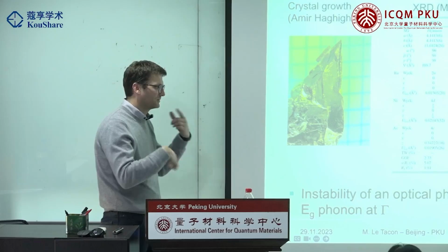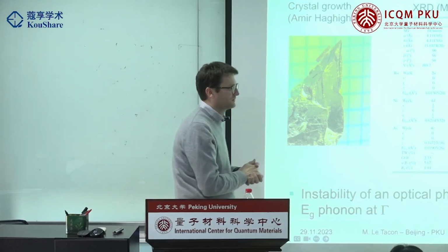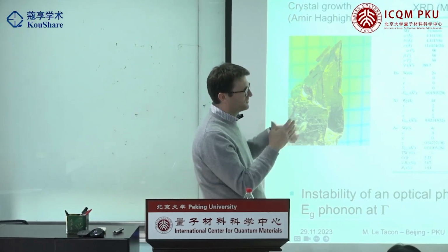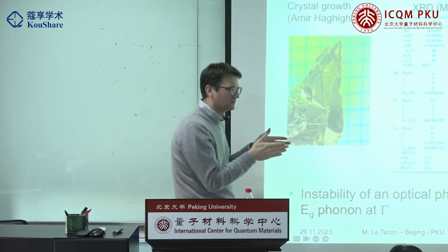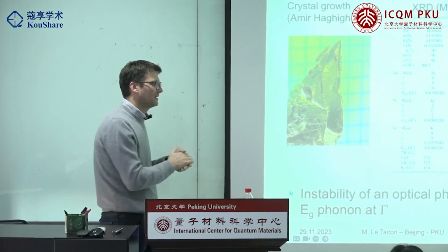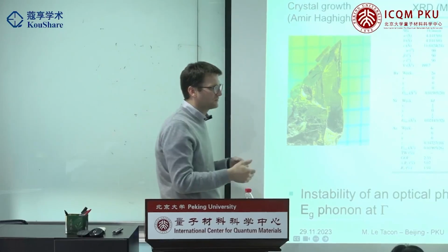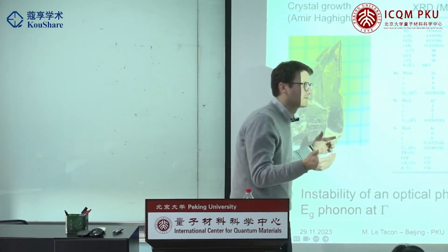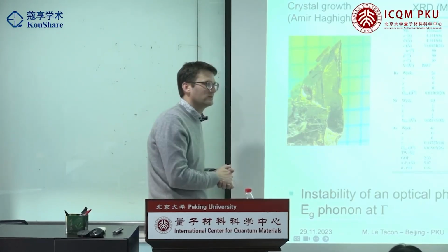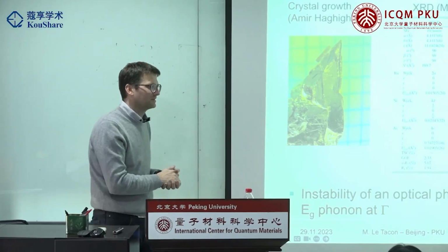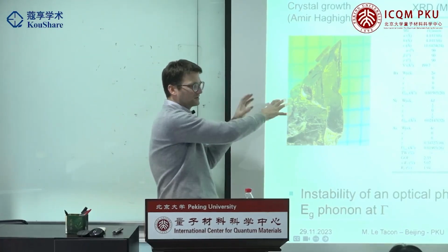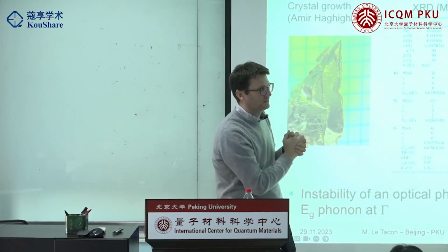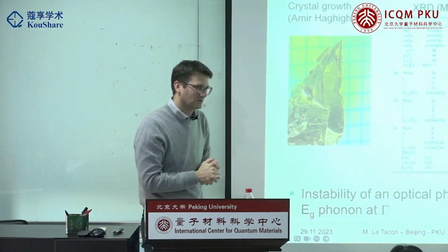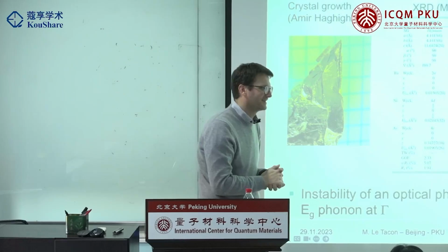So maybe just to revise those measurements, either in the narrow temperature range above the triclinic transition, or in the phosphorus doped compound at 10%, where you don't have a triclinic transition. This would be very interesting and, in my opinion, very insightful as far as the physics of that incommensurate charge-density wave is concerned, and to decide whether we can call that a charge-density wave or not.